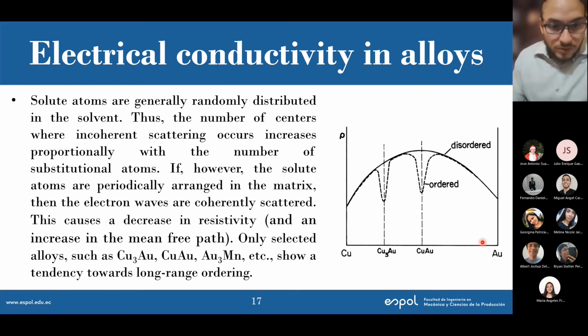But again, there are only few alloys that have that tendency, right? And among those are the ones you see there: copper gold, or Cu3Au, gold 3 manganese. So those are the alloys that show it. There are more obviously, but it's quite difficult to get this tendency of alloys towards long range ordering. Okay.